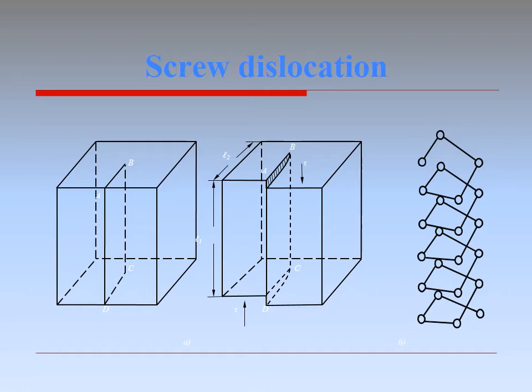Since the incision ABCD only reaches the middle of the crystal, the right part cannot move entirely by one lattice period. The displacement of the right side decreases in the direction from point A to B. The top atomic plane is curved. Similarly, in the second atomic plane from above, the first part of it from the front edge is shifted by one lattice period and merges with the third, and so on.